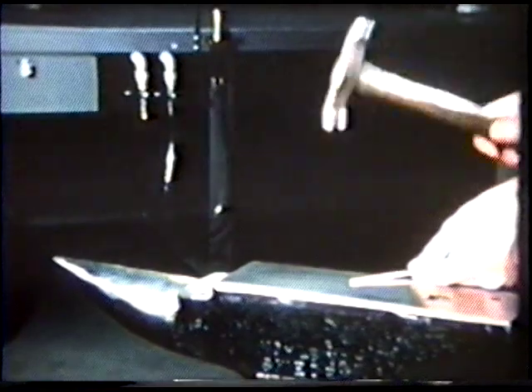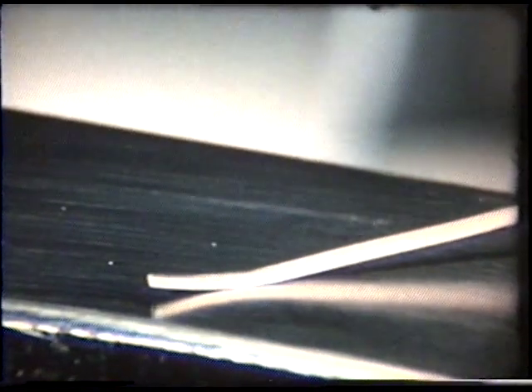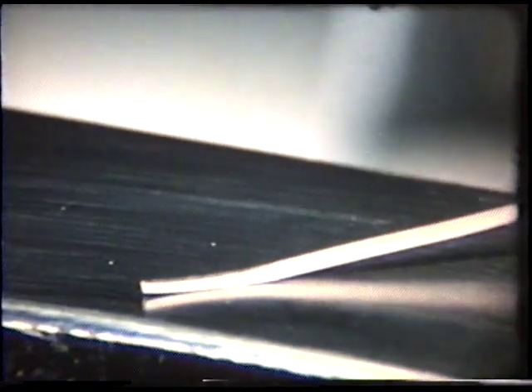An anvil and a planishing hammer are used to forge 14-karat square gold wire to begin the forming of the pieces which will become the legs of the beetle. Gradually the square wire thins and assumes a tapered shape. As the piece thins, the compressed metal flares the flattened end.